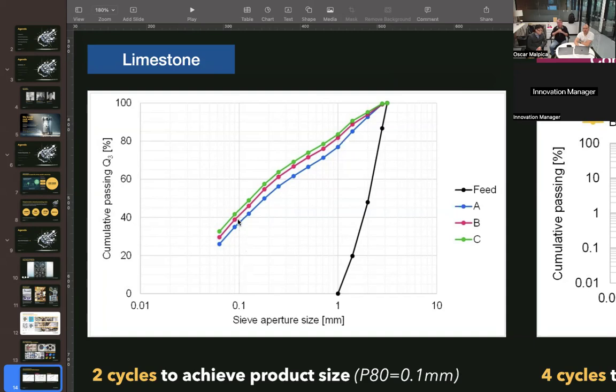And so the way the industry typically uses a single number to represent how much breakage, or the size fraction of material that you've broken, is using P80. The P80 is the 80% line across the top of this chart. If we were to take this material and produce a P80, say at 0.1 millimeter, you can see that we only need to run it at 2 cycles. So we get 40% breakage in the first cycle and 40% in the second cycle, which would produce 80%. So that shows, for limestone, we're talking about 2 of our pressure cycles to break that material down.